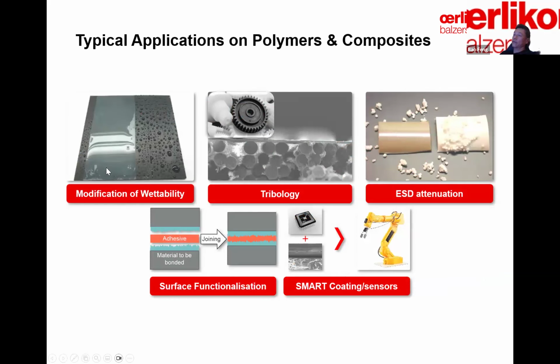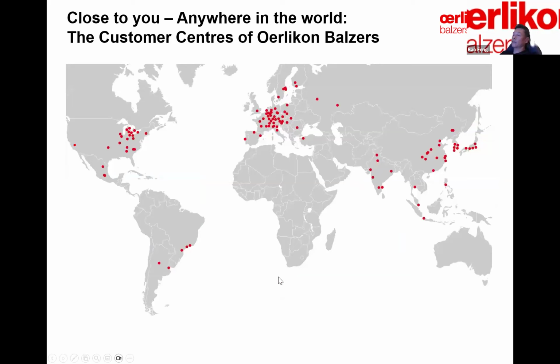Or we can use the coating to modify the surface energies or the wettability of the surface. For example, for molding tools, I want to create this easy release function between the workpiece and the molds, and also provide a wear protection to those molds because the molds are very expensive. Or for plastic gears, reinforced with carbon fibers or glass fibers, those fibers are very abrasive to the counter surface. So we will lay down diamond-like carbon type of coating on top to reduce the friction and reduce wear to the counter surface. Or we talk about the electrical conductivity of the coating. It can modify the static charge situation on the surface. So on and so forth. We can brainstorm endlessly for different applications.